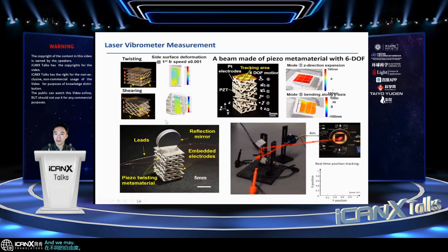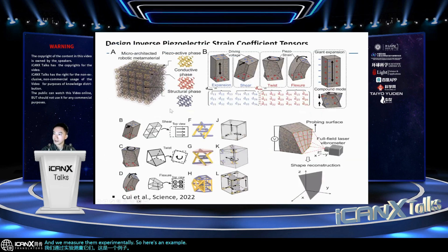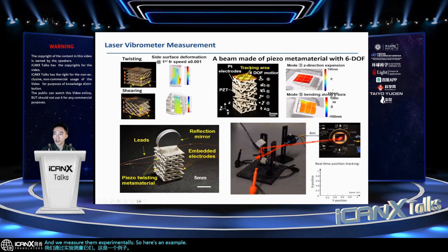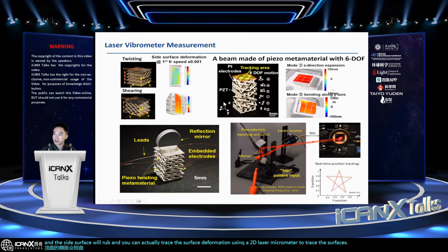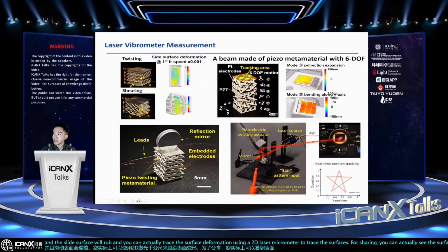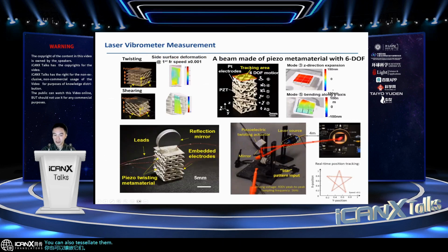And we measure them experimentally. Here's an example using laser vibrometer measurement to measure the deformation of these metamaterial blocks. You can trace the surface deformation. For example, for twisting deformation, you apply a voltage, the top surface will twist, and the side surface will rotate, and you can trace the surface deformation using a 2D laser vibrometer. For shearing, you can see the surface being deflected in different directions. You can also tessellate different metamaterial unit cells in 3 dimensions so that you can select different motions. So here's our motion that has 6 degree of freedom actuations.